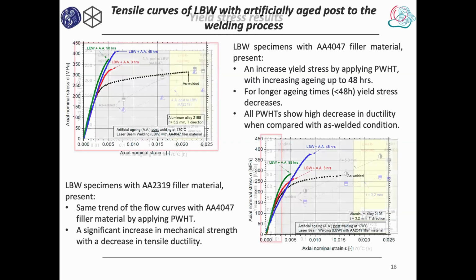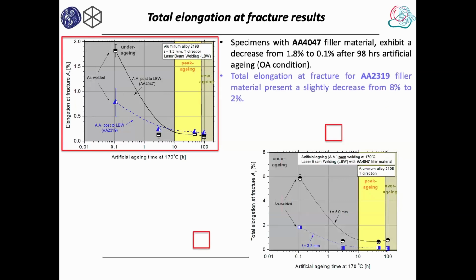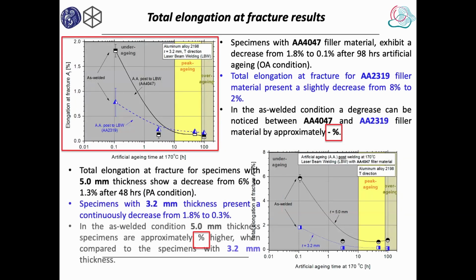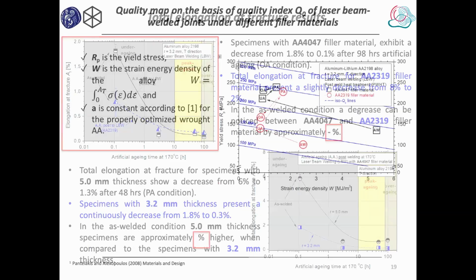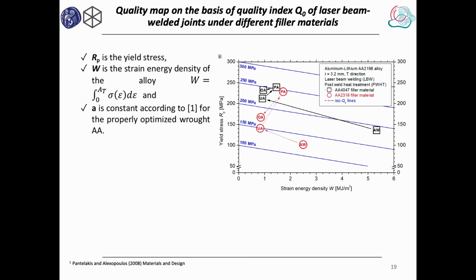And also Professor Alexopoulos proposed a method for characterization of mechanical performance of the welded joints by means of the quality index. The quality index is the energy required to introduce the deformation into the specimens up to the failure of the specimen. And the higher the energy is, the higher the quality of the welded joints. And here the welded joints were also evaluated with regard to their quality index to find a good criterion for assessment of the welded joints.